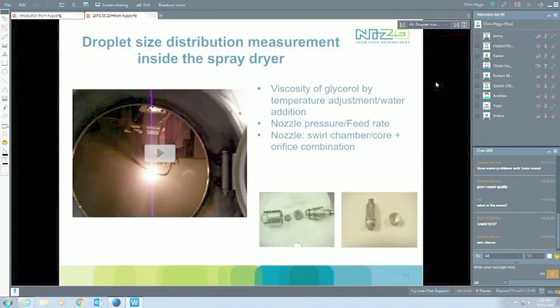What we ended up doing there was basically saying, okay, how can I know my droplet sizes? What atomization conditions do I need, what nozzles do I need to get optimal sizes? Apologies, there was a movie, but that's not working, unfortunately. We ended up doing particle size measurements inside the dryer, looking at different nozzles, different orifices, different pressures, temperatures, anything like that. And you can really measure your atomization, and you can start getting decent measurements of your feed and see how it atomizes. The only issue there is, if we put milk on that, then our particle size analyzer will be fouling in 2 minutes, and we cannot take any measurements anymore.